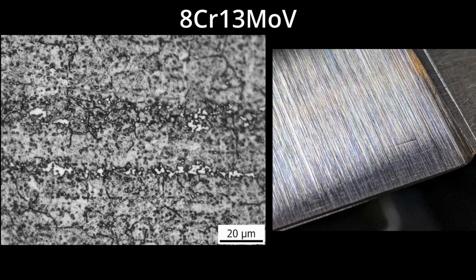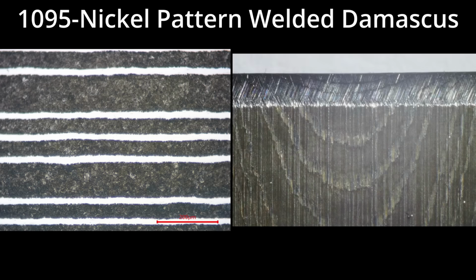So we've seen this in other steels, like in the study I did on 8CR13 MoV that had some banding in it, and that helped its edge retention. We also saw that in pattern-welded Damascus, where we intentionally got a banded structure, and that also boosted edge retention. So the edge retention of the Wootz was helped by the high carbide volume and also the banding.